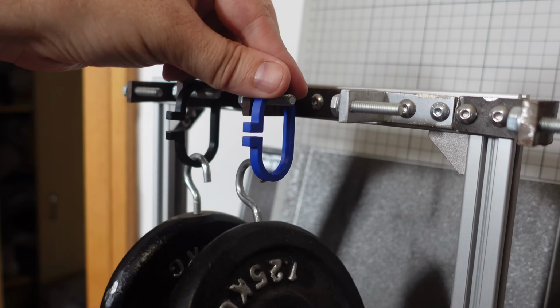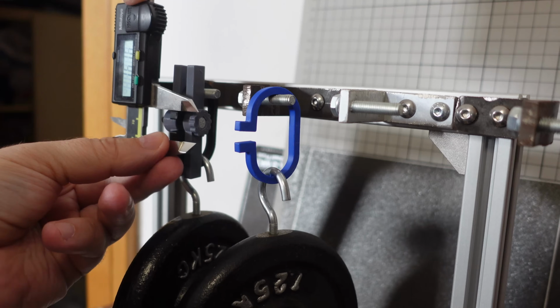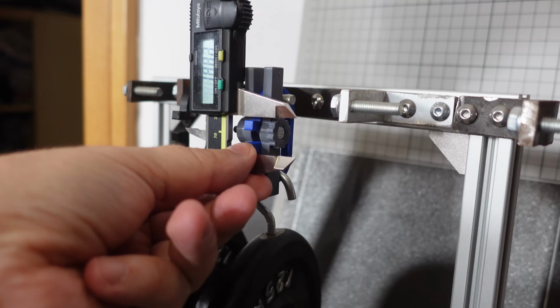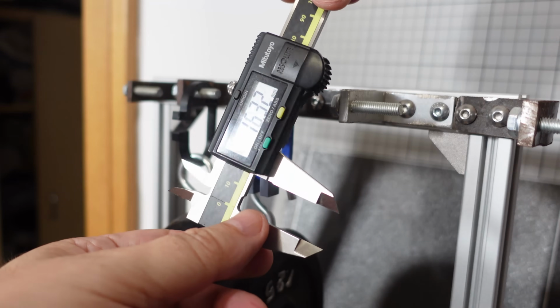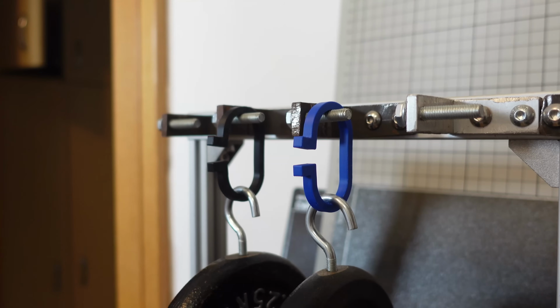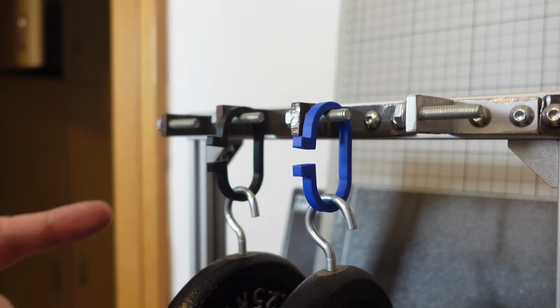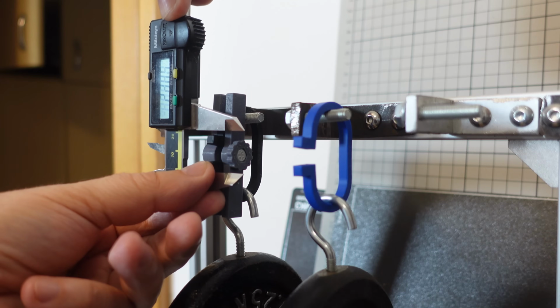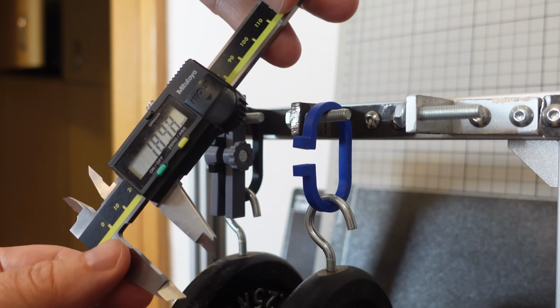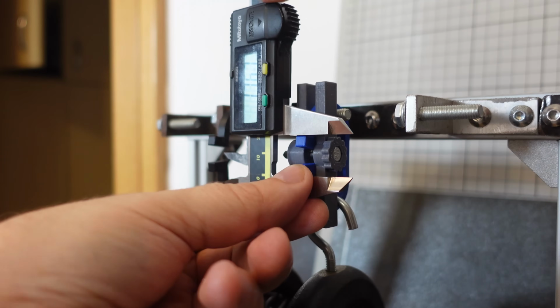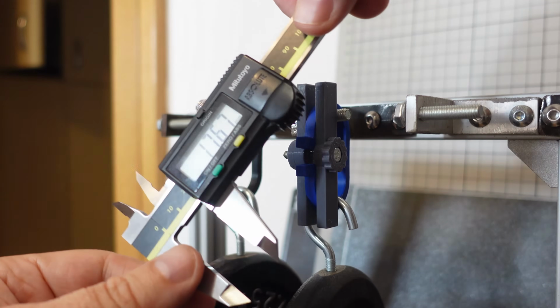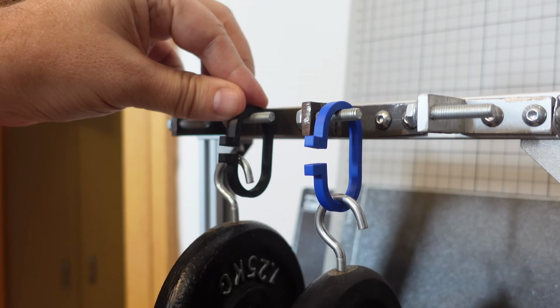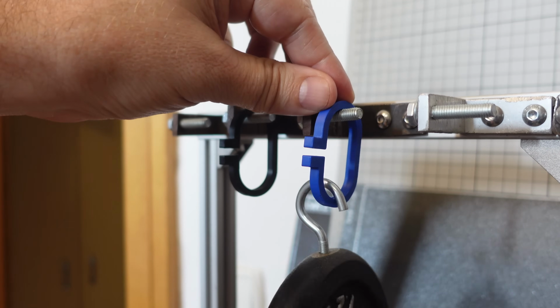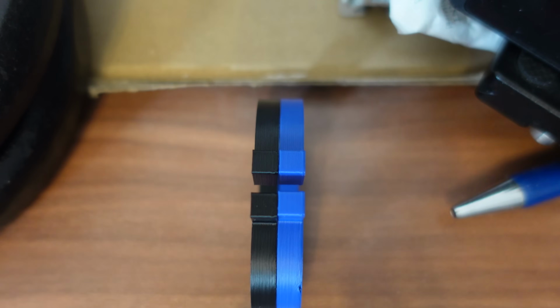Creep test, the deformation under the constant load, which is 1.25 kilograms: 16.76 on ABS part and 16.32 on ASA. After 5 days, even with the bare eyes, I can see more deformation on the ABS part, but let's measure it. 18.98. 17.67. Removing of the load. After the test, I can see very minimal permanent deformation on them, but they are very equal, hard to see any difference with bare eyes.